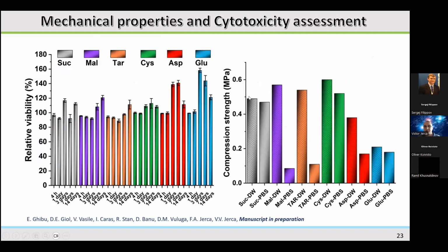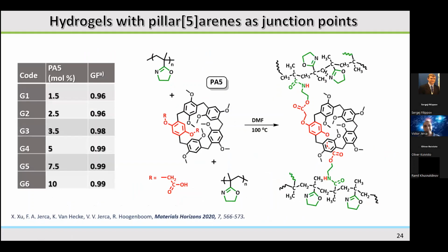We tested this also by compression experiments, and as you can see, the compression strength after incubation in PBS drops dramatically for the malic and the tartaric acid. The other hydrogel, which was used in this case to show that there is no degradation, keeps a similar compression strength after 2 weeks of incubation in PBS. We also performed some cytotoxicity studies, and we showed that the degradation products of these hydrogels are non-cytotoxic.